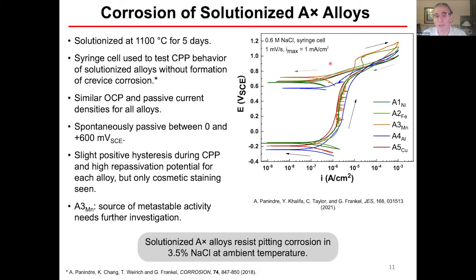So these are all of these alloys in the 0.6 molar, 3.5 weight percent solution. And you see, again, some small hysteresis coming out of the transpassive region. The manganese alloy is exhibiting considerable metastable activity, which is going to need some more work. But all of these are spontaneously passive, with no evidence of pitting or crevice corrosion in this chloride solution. So if you can eliminate a crevice effect, they are extremely resistant to pitting corrosion at ambient temperatures.